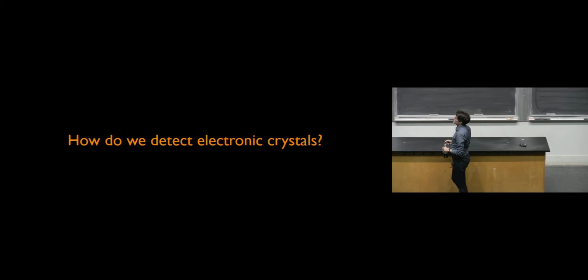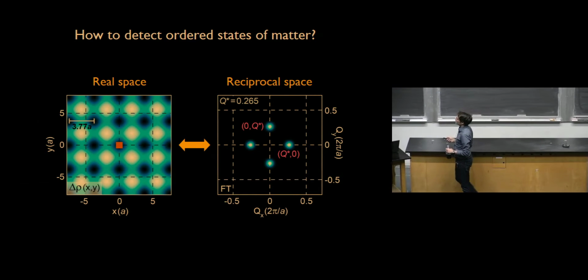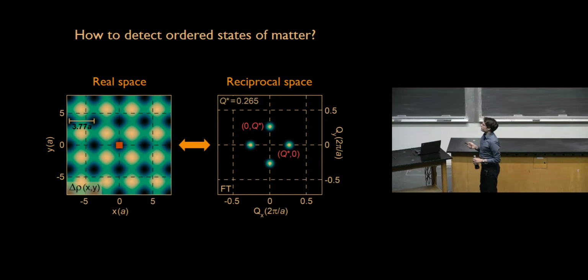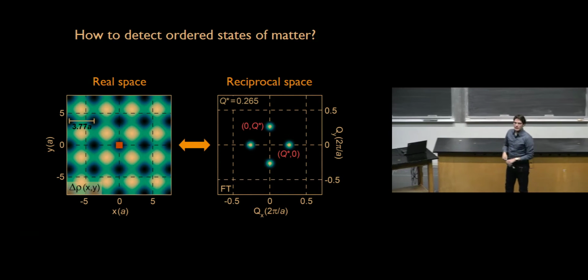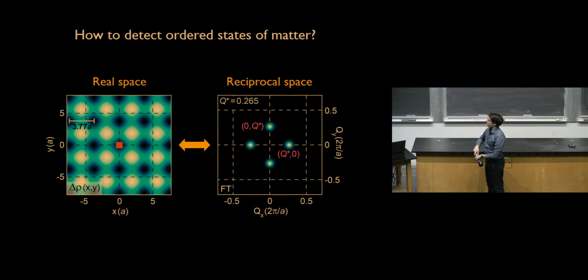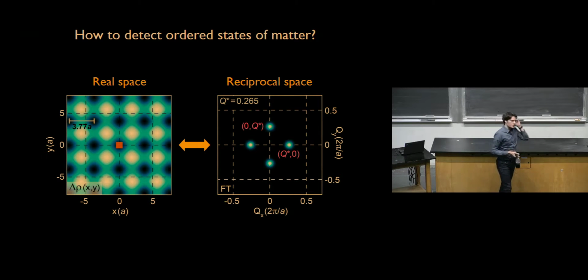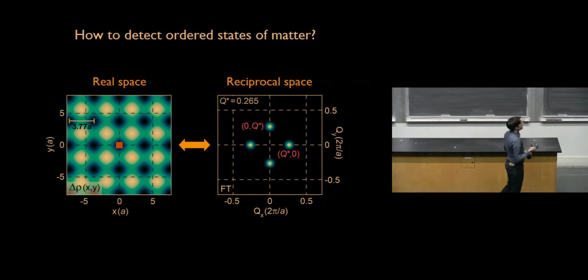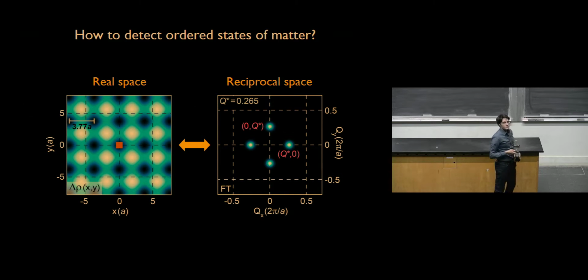So now the question is, how do we detect electronic crystals? Electronic crystals form ordered patterns in real space, which means that they have certain periodicities and form certain static orders in real space. So they are periodic with respect to some kind of operation. It could be a rotation, it could be a translation. When we take the Fourier transform of an object which is periodic in real space, then typically that produces peaks in reciprocal space. Those are just the Fourier harmonics in reciprocal space of something which is periodic in real space.